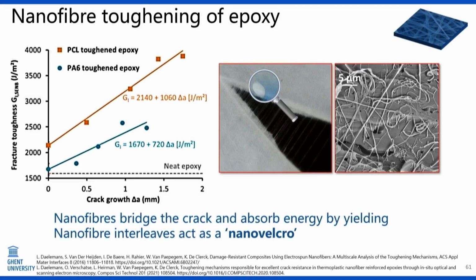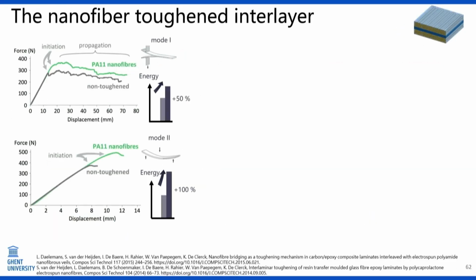So if we look at the matrix reinforced with nanofibers, then in this graph, this illustrates the energy needed to create a crack. If you use a neat epoxy, then at a certain energy level, you will initiate a crack. But once you reach that energy level, the crack will propagate immediately, and you will have immediate uncontrolled failure of your composite material. By introducing nanofibers in there, we have first of all increased the energy needed to create the crack, but also if we want to open up the crack further, we need more and more energy. And this is due to the energy absorption by yielding of the ductile nanofibers. And thus the nanofiber matrix. So we've illustrated that in the matrix, but now is this also present in a composite material?